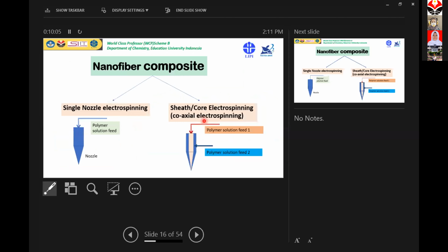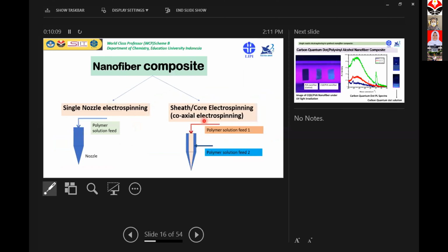Okay, to make nanofiber composite by using electrospinning, there are two main techniques. We can use single nozzle electrospinning, meaning we use a single polymer solution feed, only one polymer. Second, when we make nanofiber composite using coaxial electrospinning, we can use two polymer solutions: polymer solution feed 1 and polymer solution feed 2. So this is the method to make nanofiber composite by electrospinning.